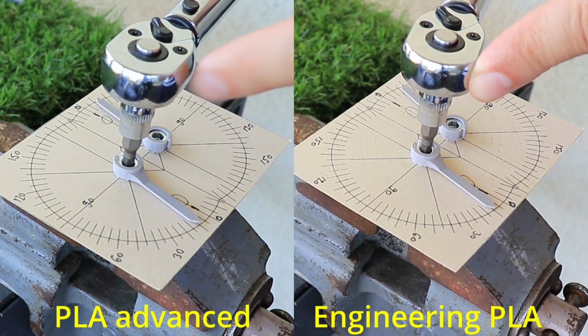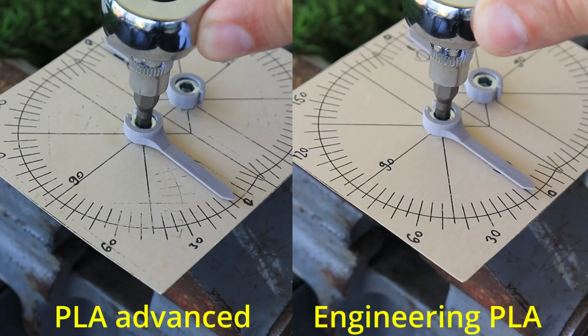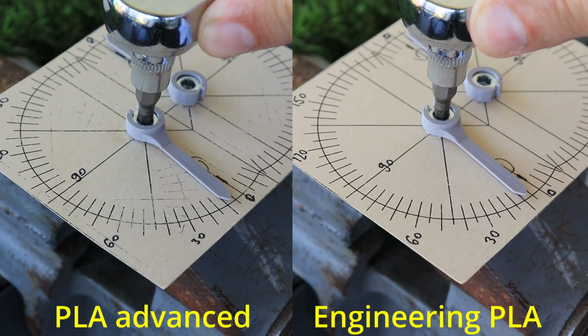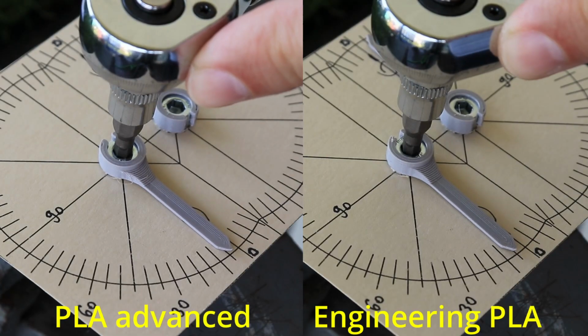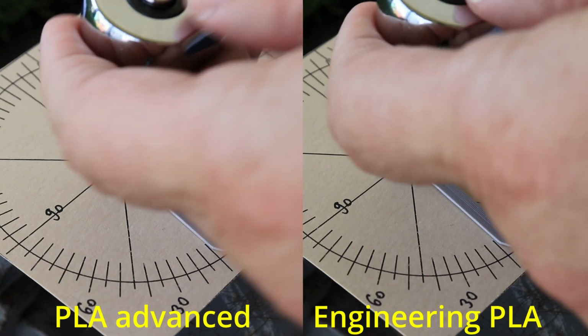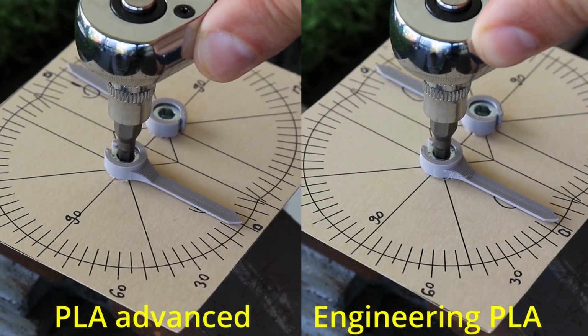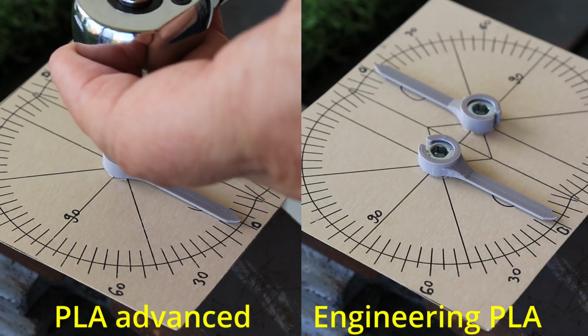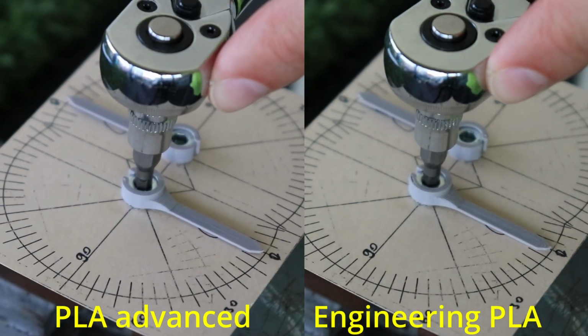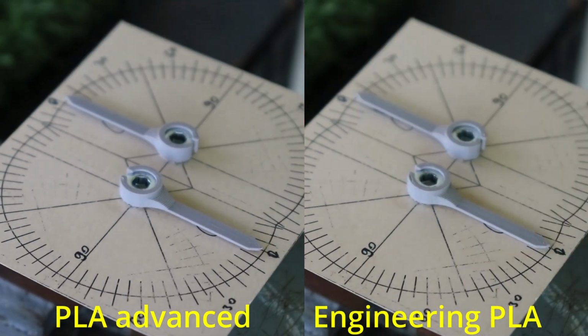This is day 1 after 24 hours. This is day 2. This is day 3, which was very hot, 36 degrees Celsius max, and after this basically the creeping stopped. This is the 5th day now, and this is after heating to 50 degrees Celsius.